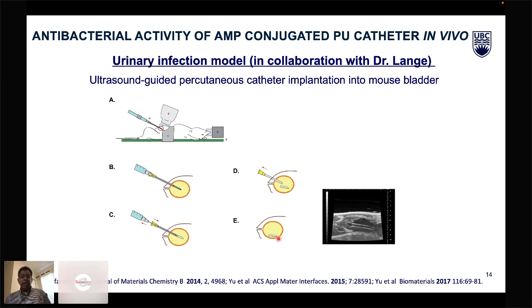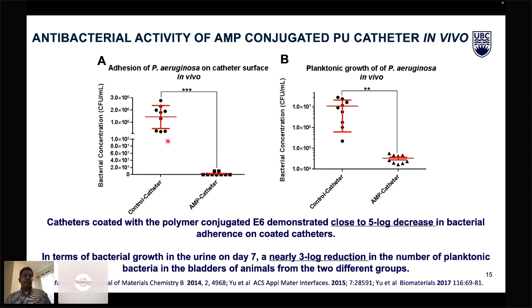So using this model, we looked at the activity of this surface, and as you can see on the left side, the catheter is able to kill the bacteria very effectively. Almost 5 log reduction is achieved here. This coating is antimicrobial, and it is also effective in killing the planktonic growth. What is growing in the urine is also killed. It is very, very gratifying to see that from a concept all the way to using a mouse model, we show a very effective surface coating